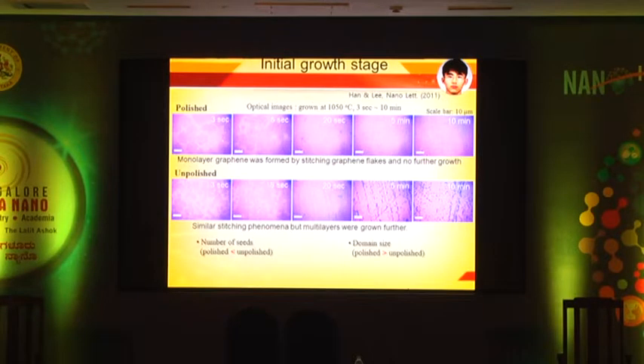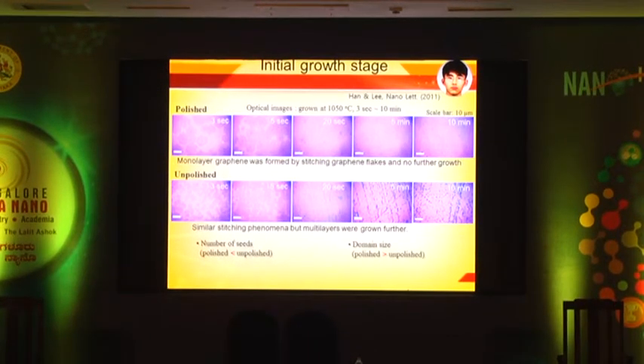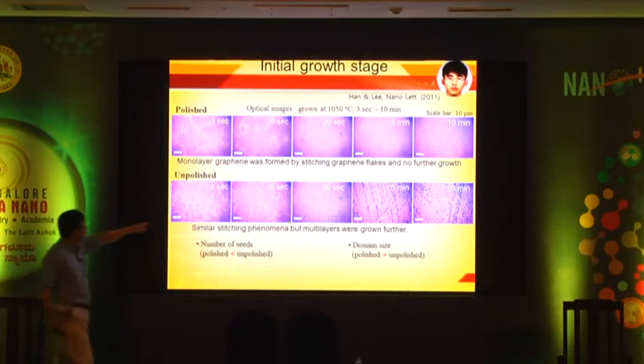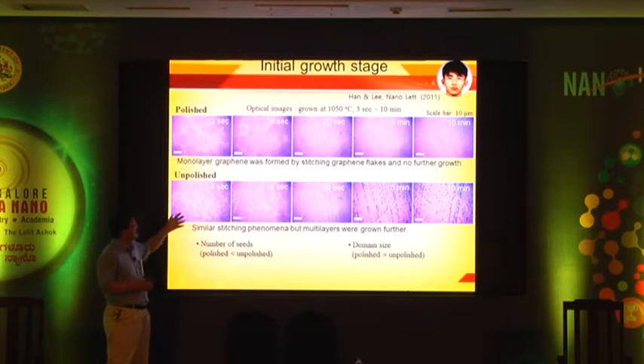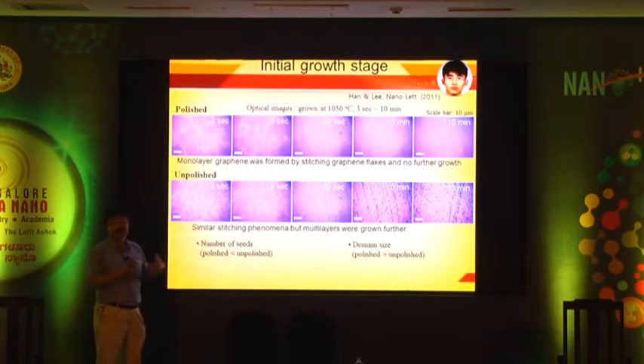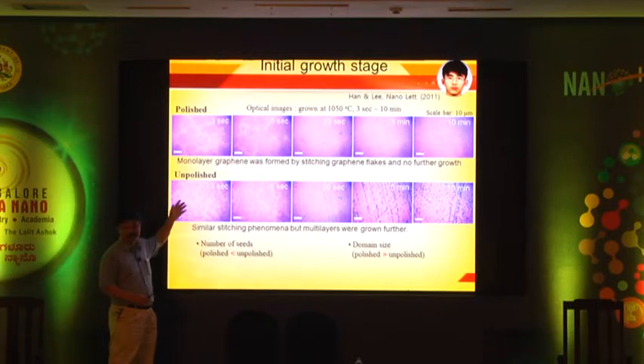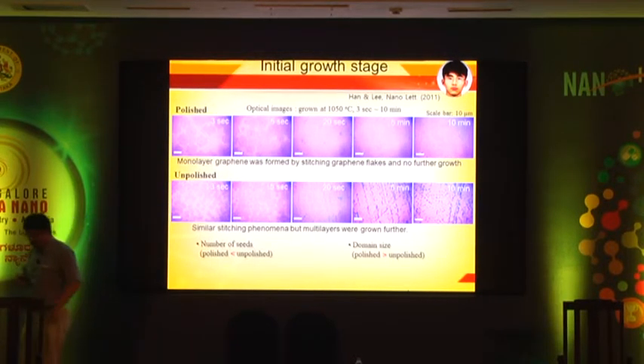If you use this very polished sample, where you can minimize the number of nucleation seeds, you see that at the initial growth stage the graphene flake is quite large. Whereas if you don't do that, the size of the graphene flakes is very small. That means when you merge them together in a large area, the grain boundary effect is more dominant in this case.